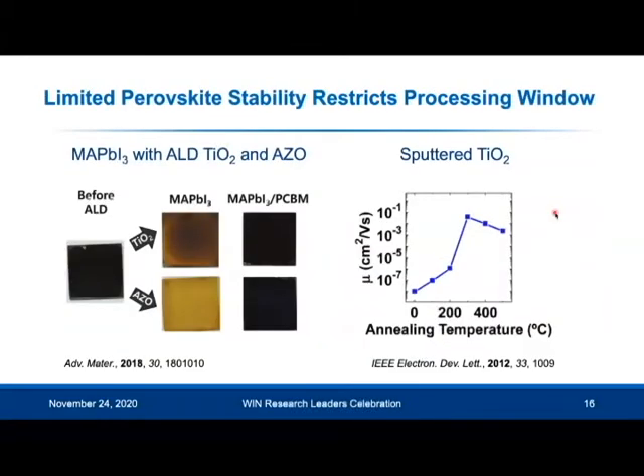And here you can see what happens if you were to use atomic layer deposition to grow TiO2 or aluminium-doped zinc oxide directly onto methylammonium lead halide perovskites. You can see that it turns yellow because the perovskites degraded when you're processing these oxides at only 100 degrees Celsius. And that's partly because the deposition time takes 1 hour in ALD. But at the same time, you can see that the higher in temperature you can process the oxides, the better the mobility is. So there are these two competing factors here.